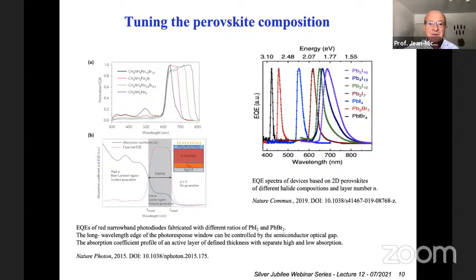As concerns the photodetectors, you can tune the perovskite composition. And like I was saying, it can tune the band gap and the range of absorption. For instance, in diagram A, taken from a paper in Nature Photonics, you can tune the absorption range of the perovskite. So this is still a methylammonium lead halide perovskite. And by tuning the composition, the ratio between iodine, bromine and chlorine, the halogen, you get different band gaps of your perovskite.